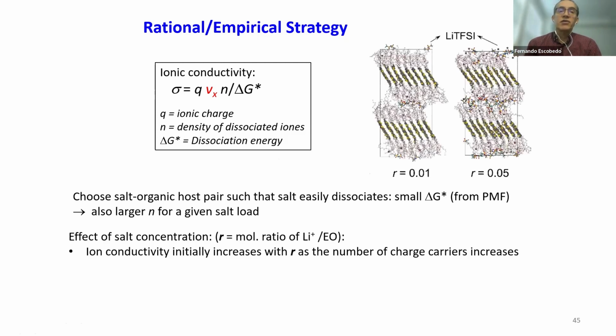Now, as far as the effect of salt concentration, that is usually quantified by this number R, which is a ratio of the number of lithium ions relative to the number of oxygens in the ethylene oxide units. What happens is that initially, as you increase R, the ion conductivity also increases, which makes sense because you are increasing the number of charges. So in some ways, you are increasing the n in this formula.